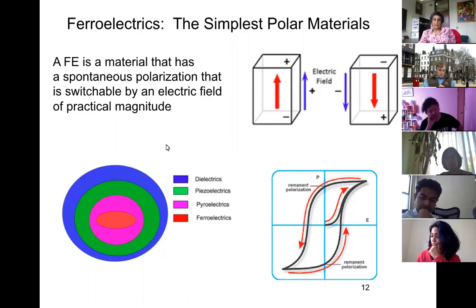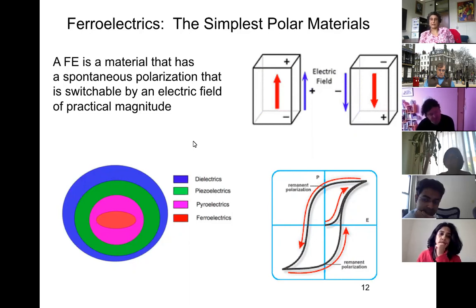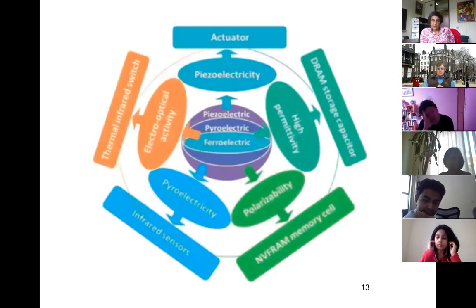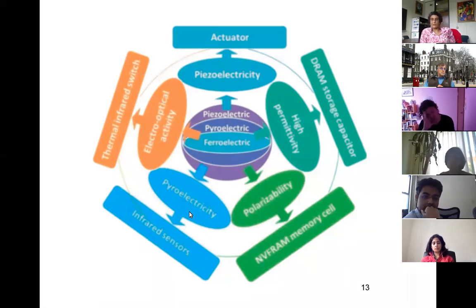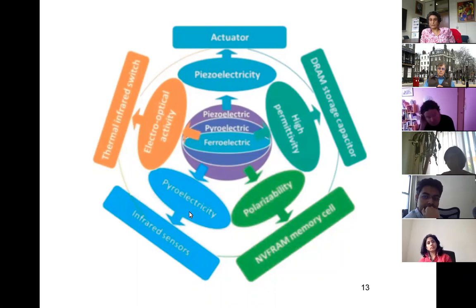Most ferroelectrics have ionic displacements and very strong electromechanical coupling, used for transducers. Ferroelectrics are used for many room temperature applications: thermal infrared switches, piezoelectric actuators, infrared detectors as pyroelectrics. A new use is cosmic radiation hardness — ferroelectric memories aren't fast compared to semiconductor memories, but cosmic rays don't affect them. I hear anecdotally that Elon Musk on his Falcon 9 actually uses some sort of ferroelectric memory. The poster child of Perovskite ferroelectrics is barium titanate, which at Bell Labs in the 70s was a fierce contender for memory, ultimately beaten out by magnetic bubble memory.